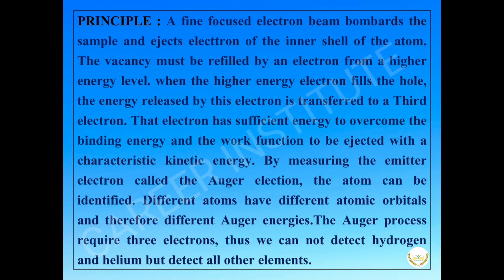Principle: A fine-focused electron beam bombards the sample and ejects an electron of the inner shell of the atom. The vacancy must be refilled by an electron from a higher energy level. When the higher energy electron fills the hole, the energy released by this electron is transferred to a third electron. That third electron has sufficient energy to overcome the binding energy and the work function to be ejected with a characteristic kinetic energy.